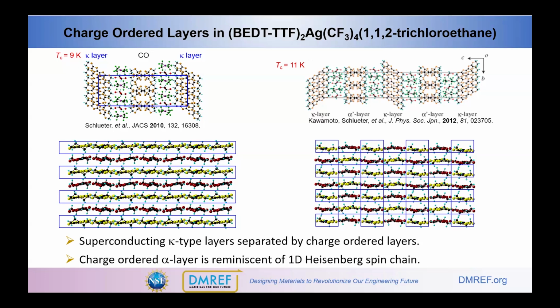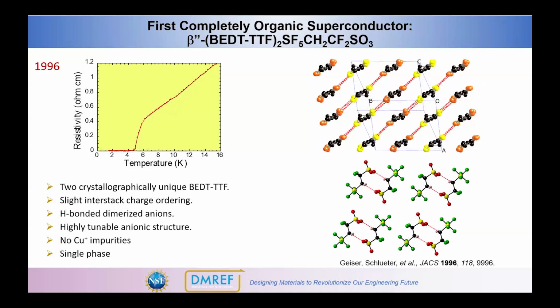in the alpha layer. I know I'm going through this kind of quickly, but it's just an overview of things that have happened and that I've been excited about over the years. In 1996, we picked this other type of anion, the SF5, CH2, CF2SO3 anion that we crystallized with ET. And this one, again, forms a superconductor, TC around 5 Kelvin. And there is charge ordering within the two different stacks of ET molecules. There's slightly different charge between the two stacks. And you can see that there are hydrogen bonding interactions both within the anions and between the anions and the ET layers.